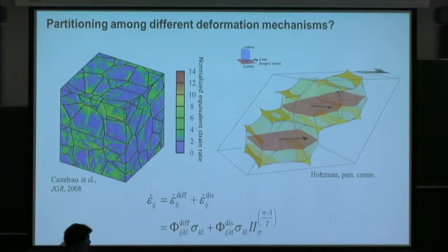And linking that into the fact that they're anisotropic is only going to aid in your ability to have some components of the strain rate tensor accommodated by different mechanisms. So what Ben suggested was that if we have an anisotropic melt distribution, so we have lower contiguity on this face, then the dominant shearing in this situation will be preferentially accommodated by diffusion creep, which doesn't have a very strong crystallographic control that we're aware of, and so would contribute less to the crystallographic rotations.